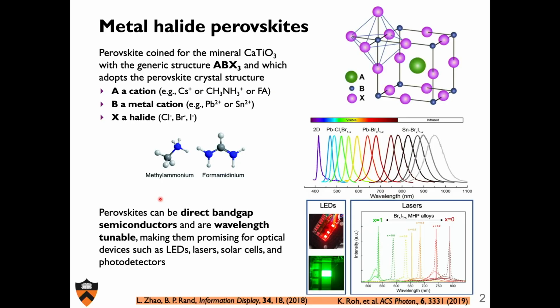So let me start with a brief introduction for those that might not be familiar with metal halide perovskites. I like to view them as, this is the unit cell, the tetragonal system here, but I like to view them as a series of these metal, in this case either lead or tin at the center, octahedra with 6 of these apical iodides or halides in general on the outskirts of it. And then you have this A site, which is positively charged, which has the right size to scaffold this system and also charge balance it to hold it together in this 3-dimensional octahedral corner sharing mantra.